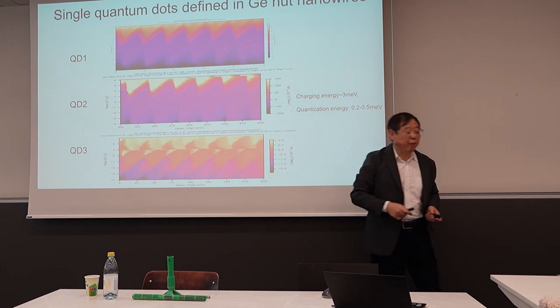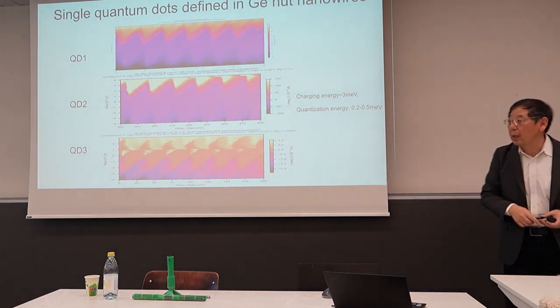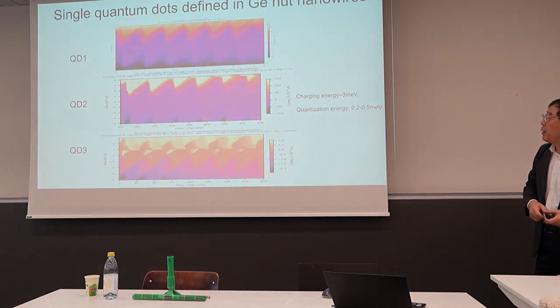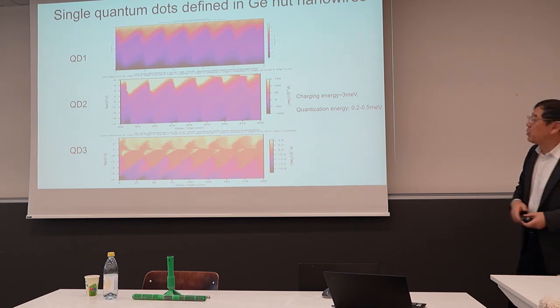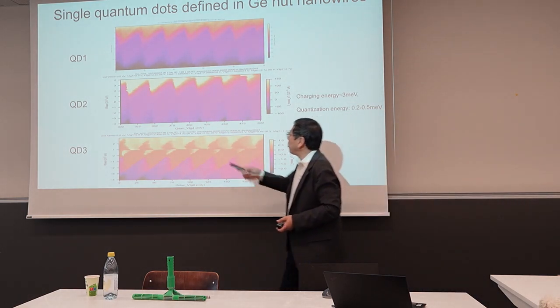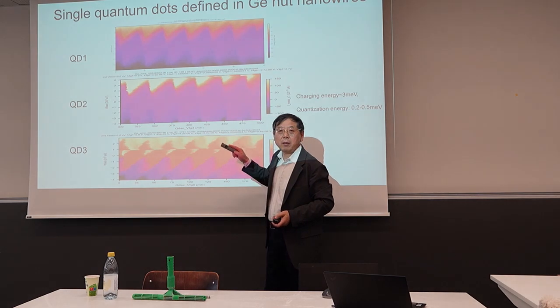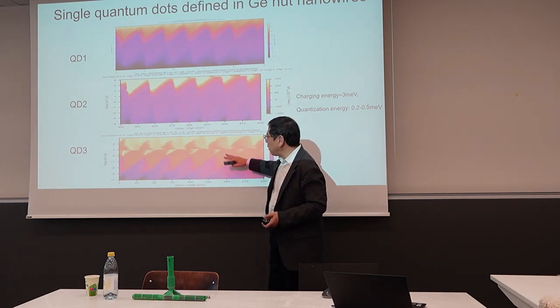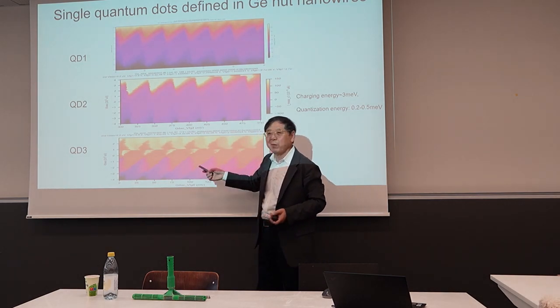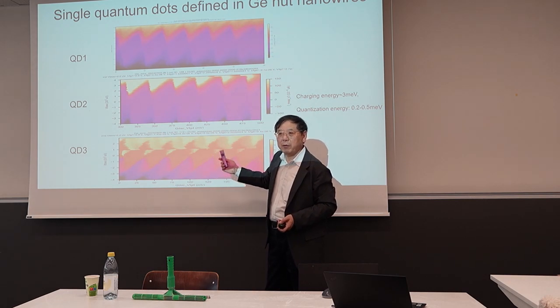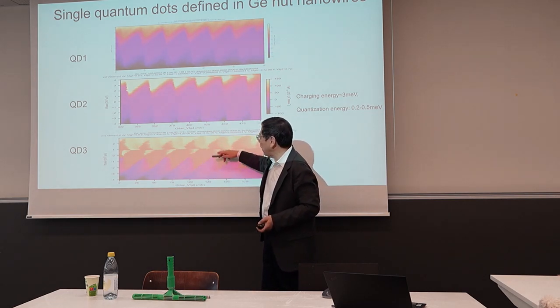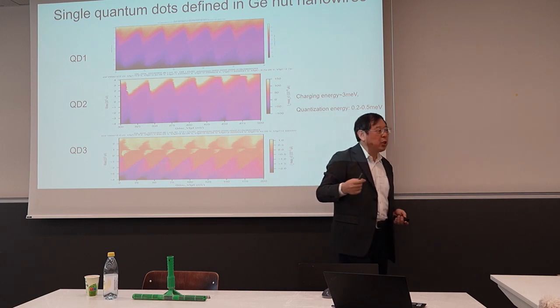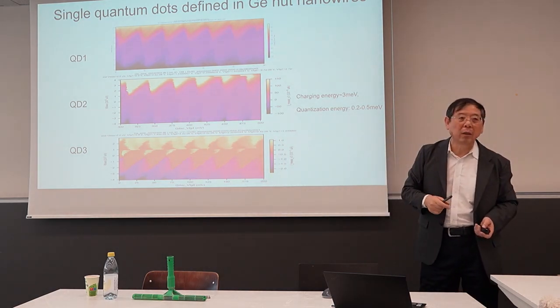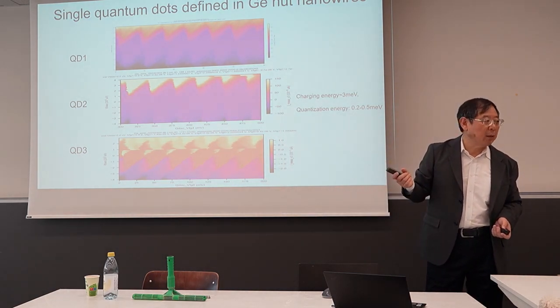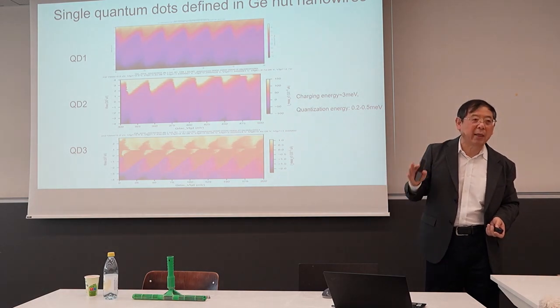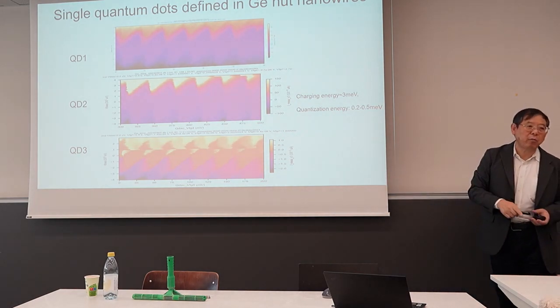And this is very fresh data. We just measured last week. It's very nice to see. It's not differentiated yet, but you see Coulomb blockade, nice, already. And this device is not good enough, that's why we have to work more. You see a lot of charge traps. So we need to change materials for the dielectric. This one we use hafnium oxide, aluminum oxide as a dielectric, which has a lot of charge traps.